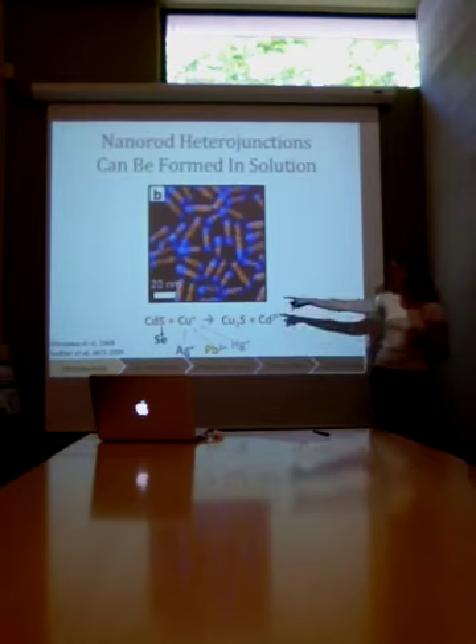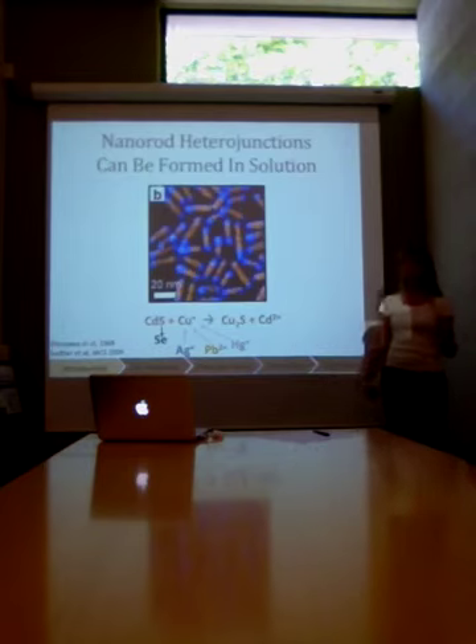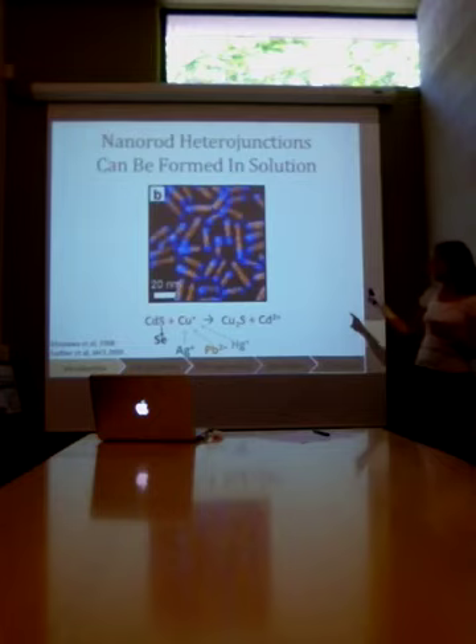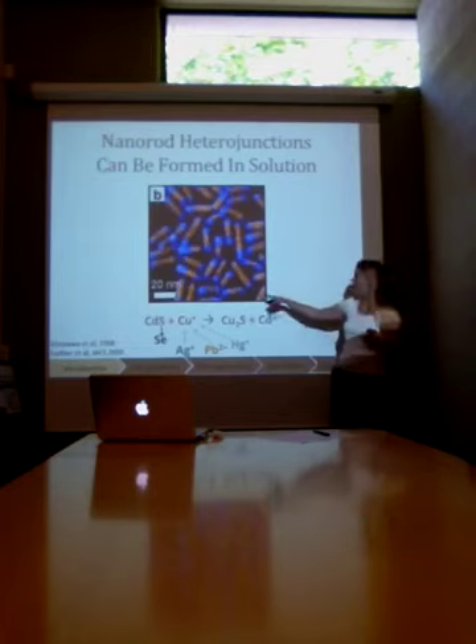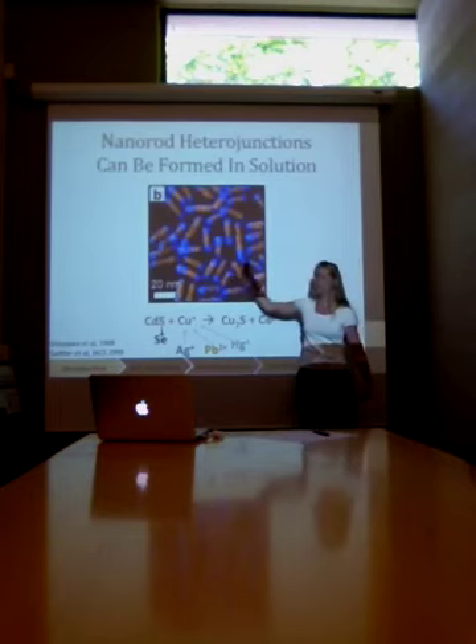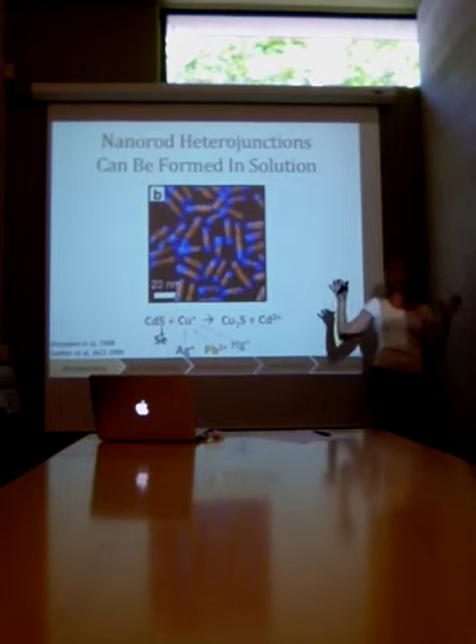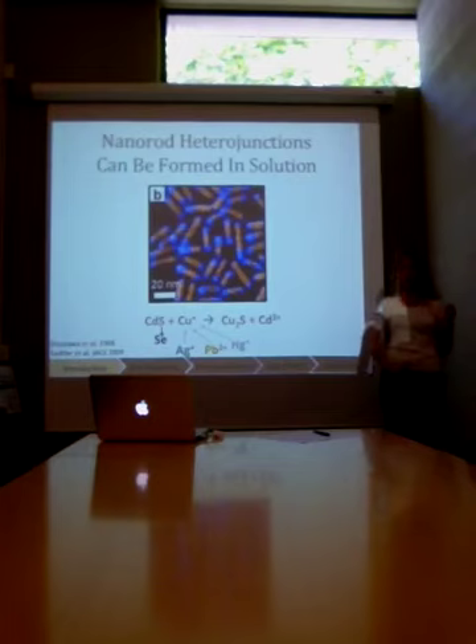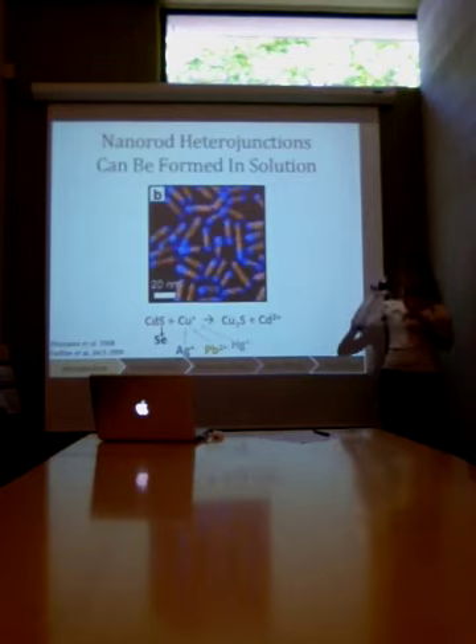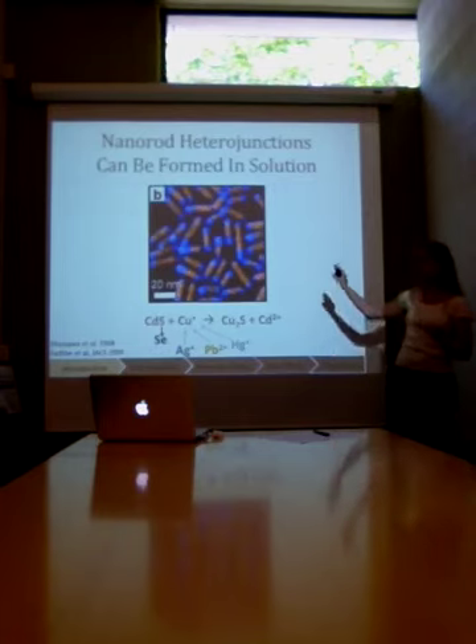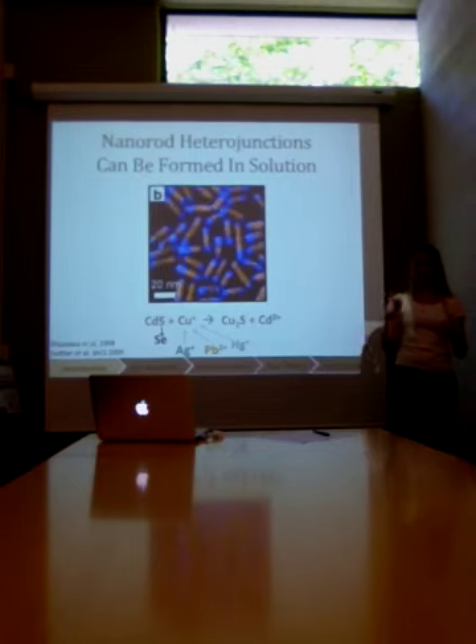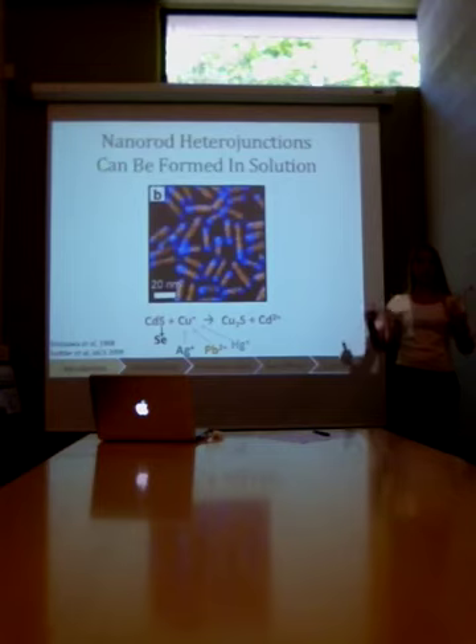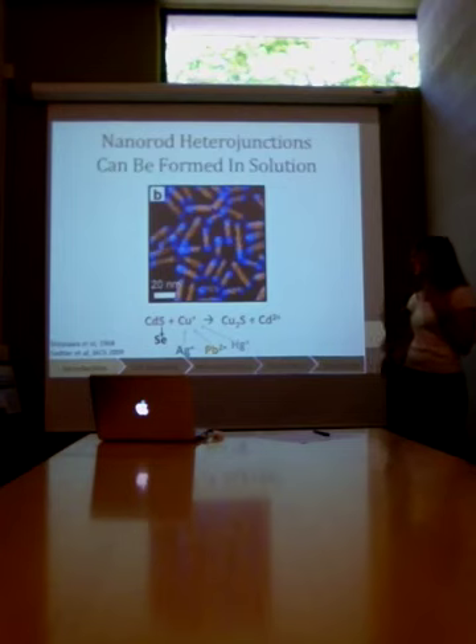And I'll note that this is generalizable to a variety of chemistries. You'll notice that in this image, most of the rods have blue ends. So we have copper sulfide coming in from both ends. And this doesn't give us the asymmetry we need to drive the electrons in one direction. We need there to be only one end that's copper sulfide, one end cadmium sulfide. But even if we were able to get this system to look like a heterojunction that is asymmetric, we still wouldn't have any guarantee that they'd all be pointing in the same direction when we assembled them. And if they cancel each other out, we're not going to get our photocurrent.